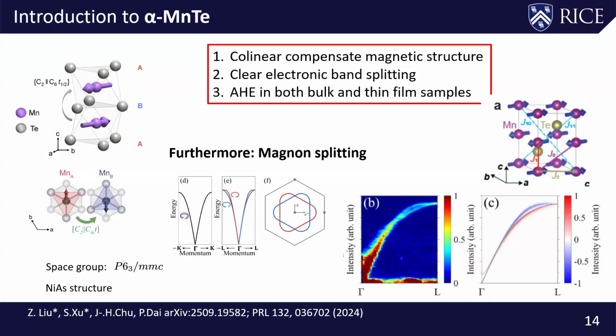Let me show you. That was what's been published, but what we actually discovered is that it's exceedingly sample dependent. So let me introduce to you why this splitting, which is not an electronic band but rather a spin wave band splitting, is actually exceedingly strange.